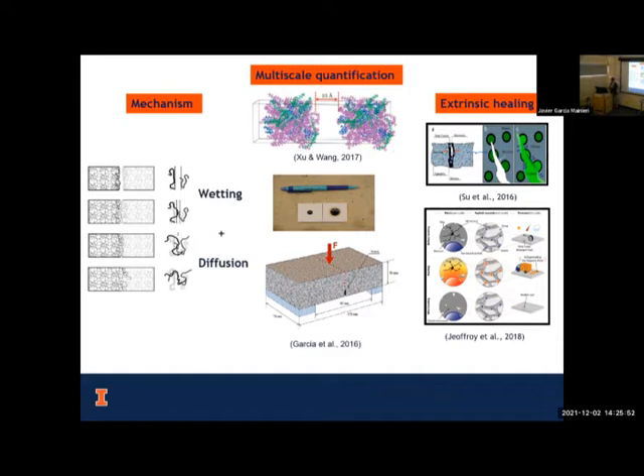We know that the self-healing capability of the binder is directly a function of the stiffness. So you add something that makes the binder softer, and this is then going to increase the healing capacity. The second mechanism is induction heating.